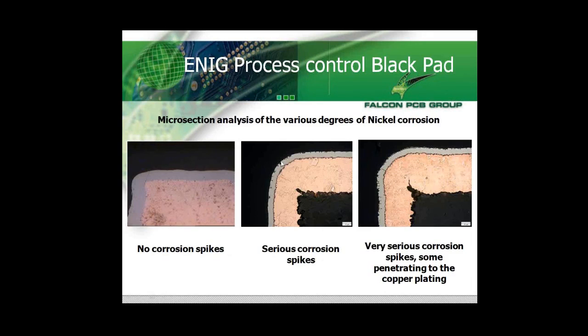Of course, if we're looking at the centre one, what we're looking at there is some form of corrosion, probably down to about 20–25% within. This board's still soldered, and it's soldered okay, but obviously it would be very worrying to look at that. On the right-hand picture, what we're looking at is serious hypercorrosion, and you can see on here some of the actual fissures go down through to the copper, and when this was done under EDAX, we did find copper peaks on the surface. Exactly what Nigel described, the copper does migrate through onto the surface of the nickel.